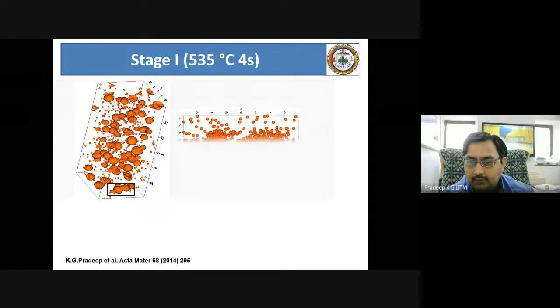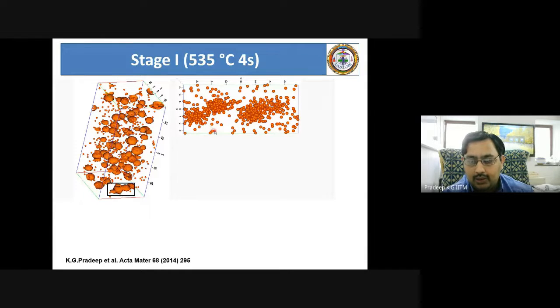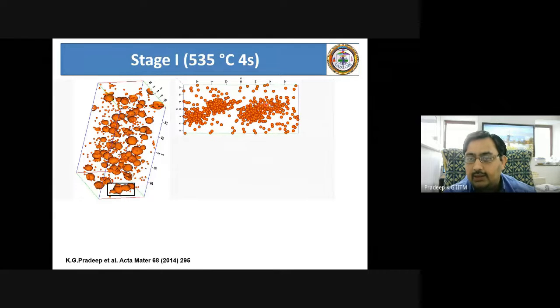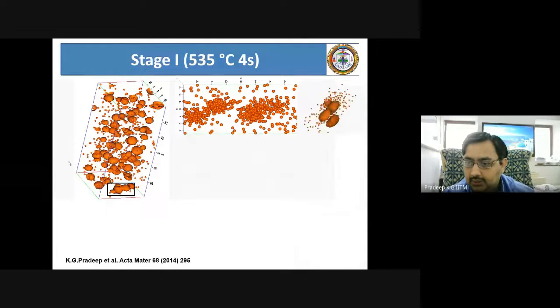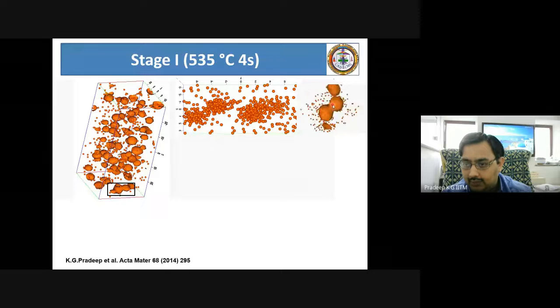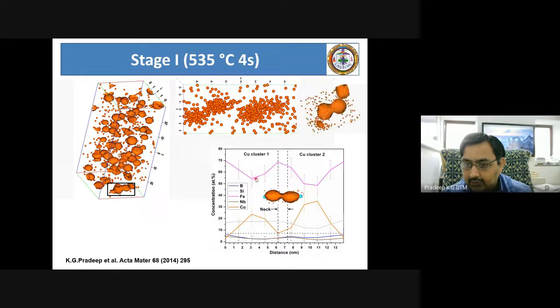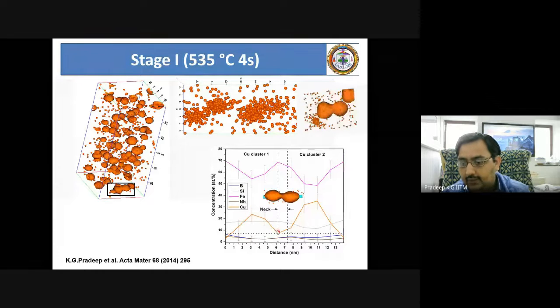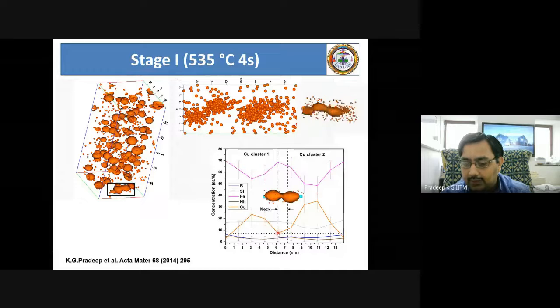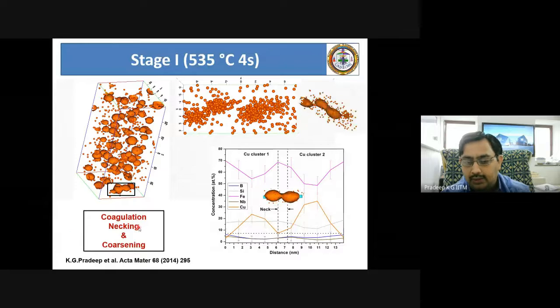Now, if you zoom in only to this part and see the individual atomic distribution, you can see here there is a large amount of copper atoms forming these kinds of clusters, whereas a bigger cluster stays isolated. 2 clusters of similar size have started forming a small necking region. Now you can further visualize this in this manner. You can see here the clusters of similar size necking. The smaller one stays isolated, the bigger one stays isolated, and you can even measure the concentration by having a cylinder going through this cluster region with the necking in between and see how the concentration of copper has increased between the 2 different clusters, which gives rise to the phenomenon of what is called coarsening, necking, and coagulation.